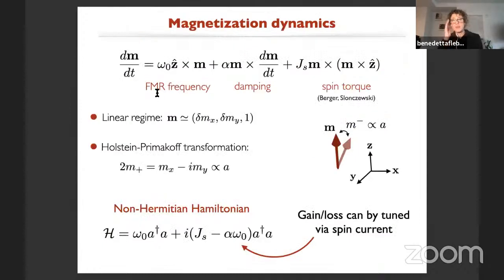So let's look at the dynamics of this isolated spin torque oscillator. Again, here we are just looking purely at the long wavelength LLG type of dynamics. So we will have some effective field that leads to an FMR frequency. We have a damping term, and now we need also to include the action of a spin torque. We can work in the linear regime, which is a very common assumption in this type of problem. So we assume that mostly the magnetization is aligned along the z direction, and we look at small fluctuations with respect to the equilibrium position. The small fluctuations can be described in second quantization language as magnons, and by invoking the Heisenberg equation of motion, we can find the Hamiltonian.